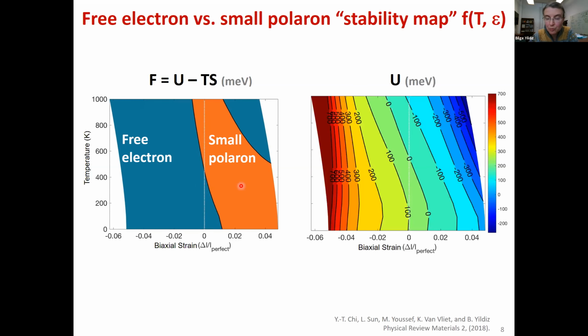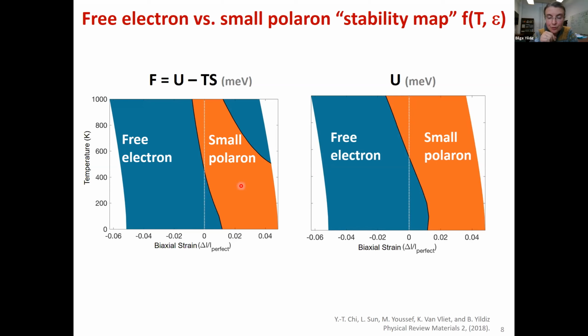And if we were to look at this problem only from the perspective of internal energy, we would get a different map where the border between the small polaron and free electron is slightly different. But more importantly, we miss this high temperature regime where free electron dominates again because the entropy contribution from free electrons is greater than trapped small polarons. So this is the more accurate map that we take. And it has implications such that, as I've already said, free electrons are more mobile than small polarons. So if in your device you desire faster electronic conduction, this would mean that you should choose substrates that give compressive strain, in-plane compressive strain to the strontium titanate.